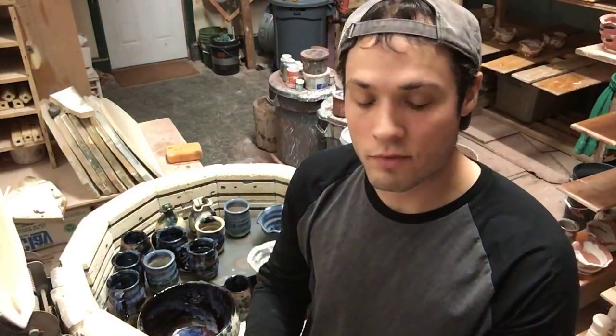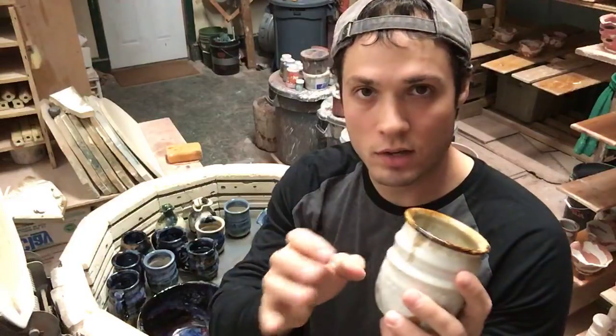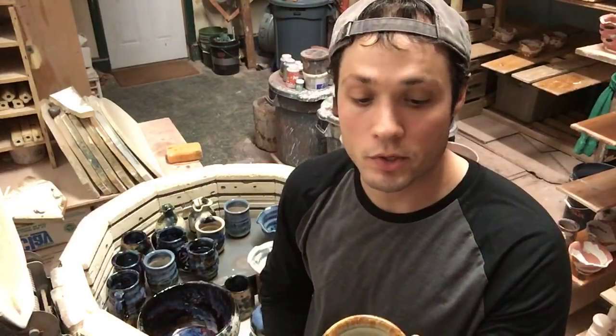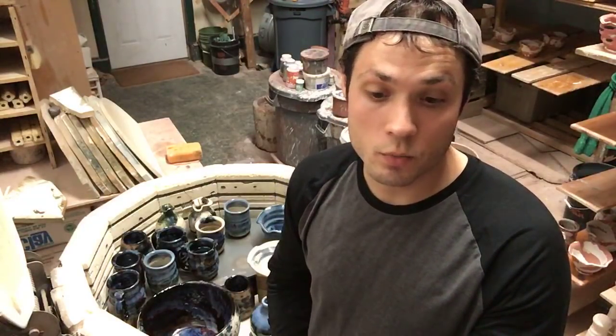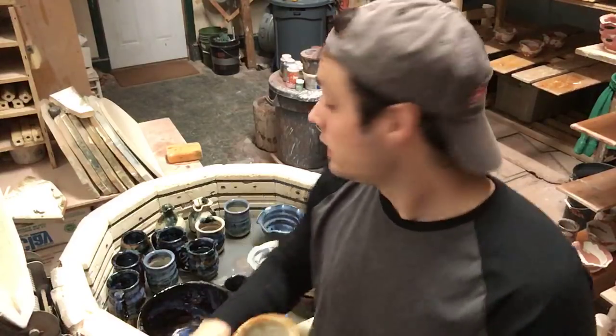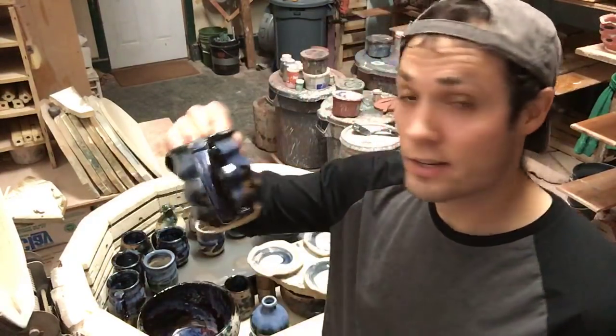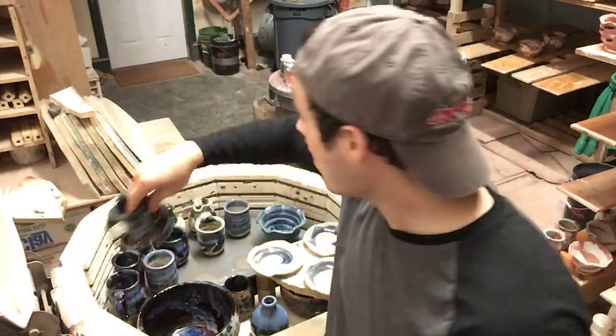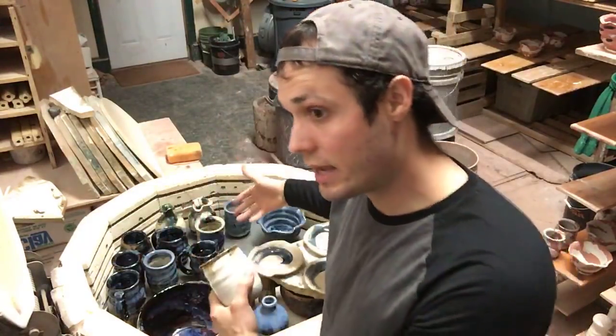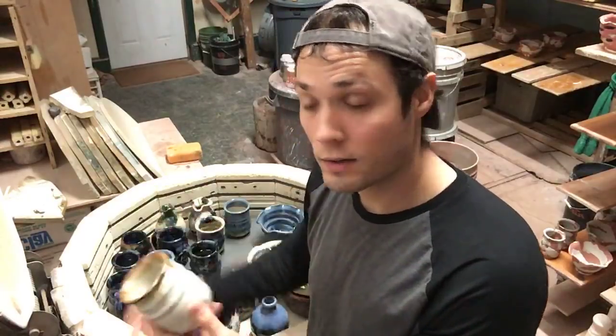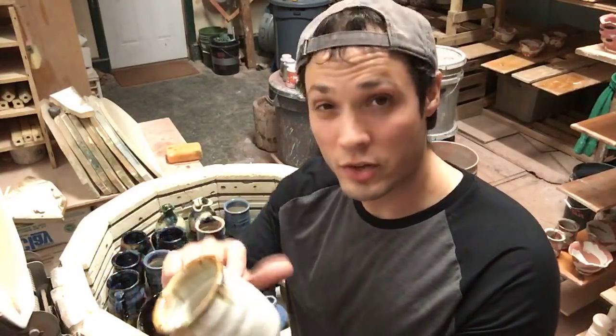There's bubbling in almost every single glaze, but usually gases come out and then they melt over at a lower temperature. So one way to solve this without changing the recipe, which can be really confusing, is to just fire hotter or fire for longer. Now, the downside is it's going to change how the cosmic glaze looks, which is already dialed in. So I wouldn't be able to fire those pots along with it. So in order to stay with a variety of work in here, I'm actually going to try to change the recipe instead so I can keep the temperature and the firing the exact same.